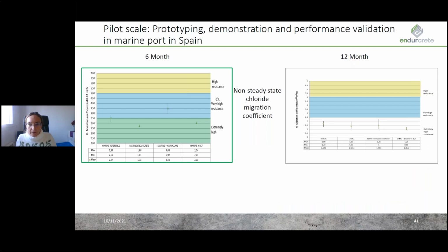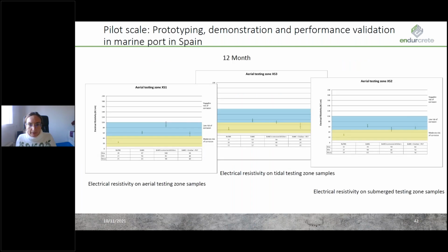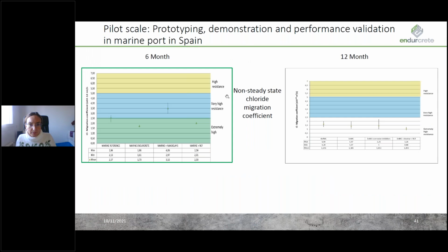Here you have some graphs, and what they are saying, as you see here, is that as time is passing, the resistance is getting better at 12 months than at 6 months. So the corrosion seems less. That's all so far. We need more time to see the performance of the corrosion inhibitors, but at this moment, we have to wait. The price of the production process was not low, but it's still in the range of the commercial products. So we have to wait for the results. And thanks so much. That's all.